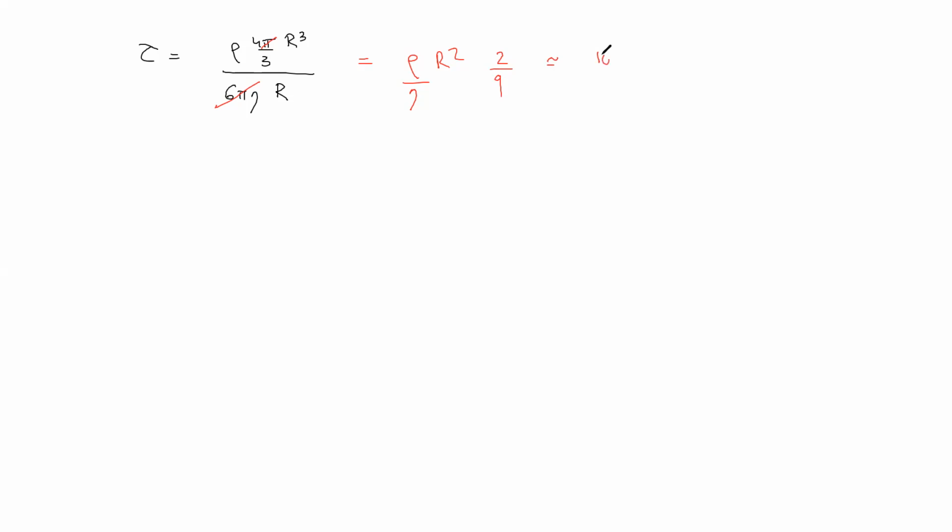Okay. And in terms of numbers, the density we will deal with typically is something close to water. The radius we estimated in the first tutorial, the typical size of a polymer chain was 20 nanometers when we were constructing that by saying it was the square root of the number of monomers times the size of a monomer, and we said this is typically 0.2 nanometers, 2 angstroms, and the number of monomers is typically 10 to the 4, so the square root is 10 to the 2. All right. So that's a medium number. You can have other values. So here it was 20 nanometers, so 2 times 10 to the minus 8.